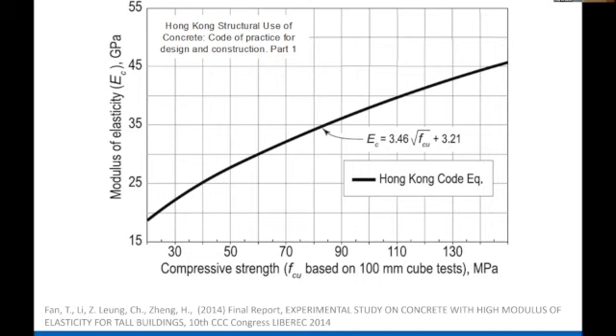If you look at it, if you want a 45 gigapascal modulus, then you need a compressive strength of 140 megapascal. But the designers are perfectly happy with 100 megapascal as far as strength. They're using this higher strength for higher modulus. But higher strength means higher cement content, higher cost, and as we know, the material is also more brittle. So is there another way?